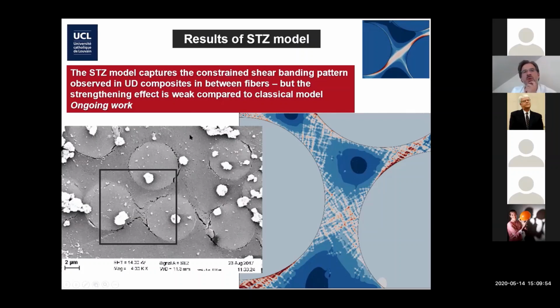But if you want to get some knowledge about the large strain viscoelastic, viscoplastic response, compression is better suited. And that's true for many high-strength polymer systems. Not so many are ductile in tension. So compression is needed, and you have to be very careful with compression because of the friction. So we use lubricant, Teflon, or different methods, and also DIC to correct for the barreling effect. But we do a lot of compression indeed. We do a lot more compression nowadays.